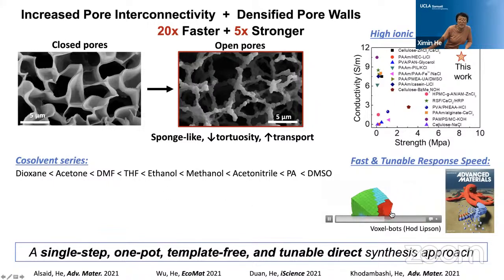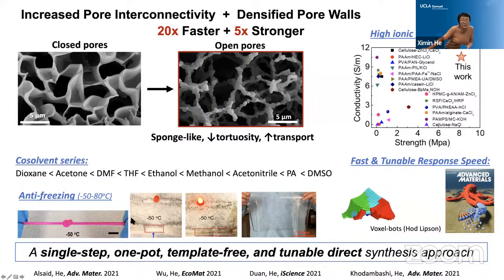With this, we have a tunable response rate of this hydrogel, for example, in the photothermal actuator that we saw at the beginning. And then with this, we're able to realize experimentally a very classic voxel-based robot model. And then interestingly, this mixed solvent sometimes can induce anti-freezing behavior, because it can depress the freezing. So this liquid-swollen gel wouldn't get frozen even under -50 or even -70 degrees